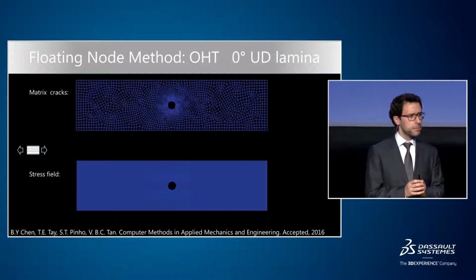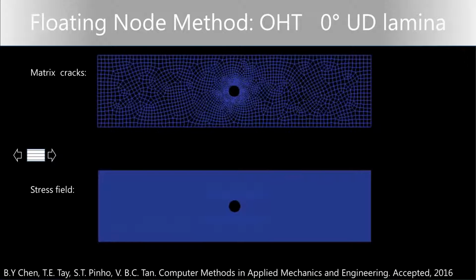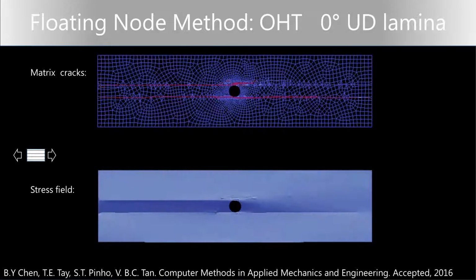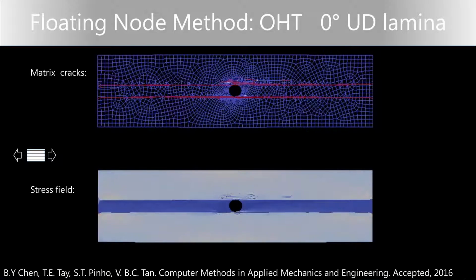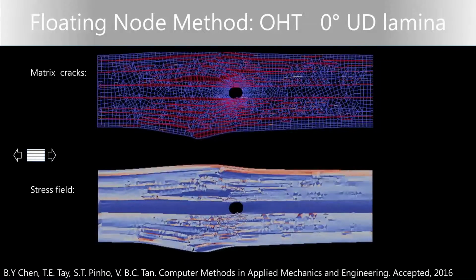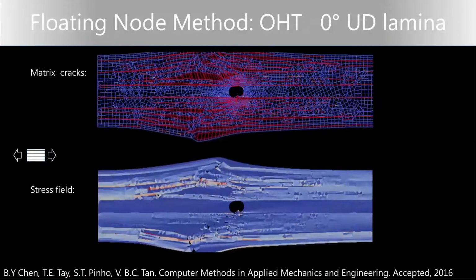So the first case, relatively simple. It's an open hole tension specimen. Open hole because it has a hole in the middle. This is a rectangular specimen, and I say it's a 0-degree UD lamina because it's made of carbon epoxy material in which the fibers are in the horizontal direction. So we are loading these horizontally, and as we do that, what you will have is splits in the matrix parallel to the fiber. In the drawing on the top, I will show you the matrix splits being formed. On the bottom, the stress in this open hole tension specimen. As you can see, the mesh has been very carefully done in a way that is not structured so that we are not guiding the direction of the cracks in any possible way. And this is final collapse with many cracks in this 0-degree lamina.